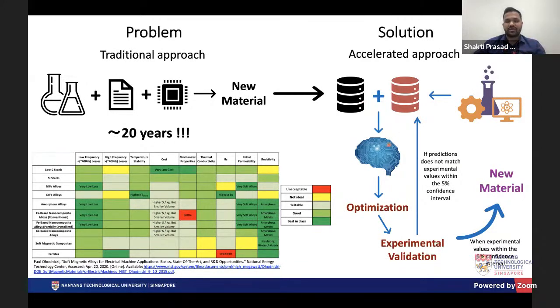After that, once we develop the model, we have to apply the inverse design methodology, wherein we go from target property values to predict composition. So basically we are going inverse. The model is from composition and processing conditions to properties. The steps involved are that we do the optimization by providing the target values for the properties. And then once we get the predicted composition and processing conditions, we experimentally validate those.